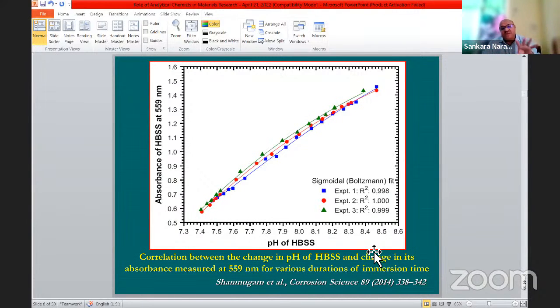So we have established this, and we have developed a simple analytical method to monitor the corrosion rate of magnesium. This paper is published in a good journal on corrosion science, and we did that a few years back. But the limitation: every study has certain limitations. The limitation of this study is that the indicator we have used, phenol red, has a limit. Beyond 8.4, there won't be any change in color. It reaches almost a pink color and then it remains stable. There won't be much change in the absorbance value beyond pH 8.4.